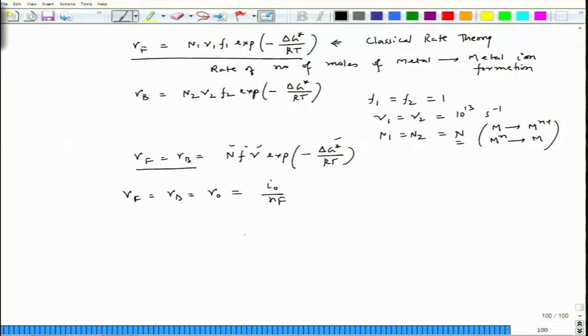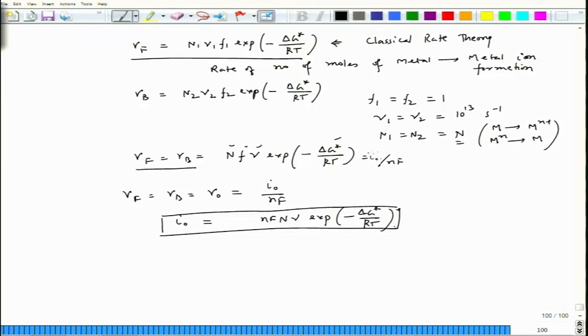So, this equal to I 0 by n F. So, I 0 equal to I 0 by n F. So, I 0 becomes n F n nu exponential minus delta G star by RT, and here F is considered as 1. So, I can remove this F. So, it becomes n F n nu. This is an important derivation, because this will be used up when we talk about polarization. So, we have an expression of I 0 with reference to the activation barrier, which is delta G star.